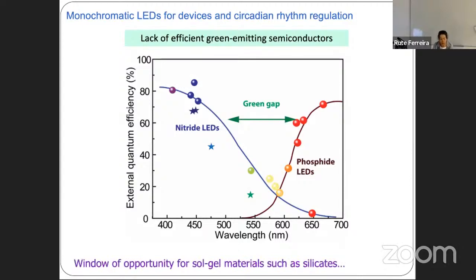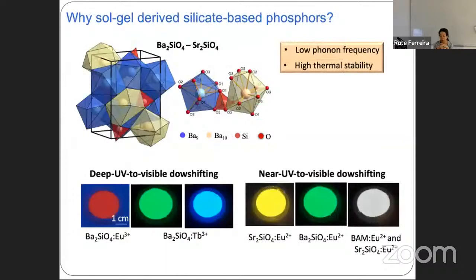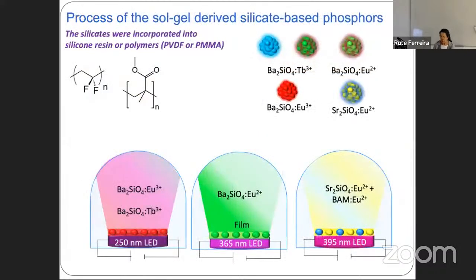There is in fact a window of opportunity for sol-gel materials such as silicates. And why sol-gel silicate based phosphors? Because they are characterized by low phonon frequency and high thermal stability, which means that we can incorporate a large amount of lanthanide ions that yield efficient phosphors with the ability to convert deep ultraviolet and near ultraviolet light into the visible. These silicates typically are incorporated into polymeric or silicone resins. Why? Because we need, of course, to process them as films so that we can develop a prototype.